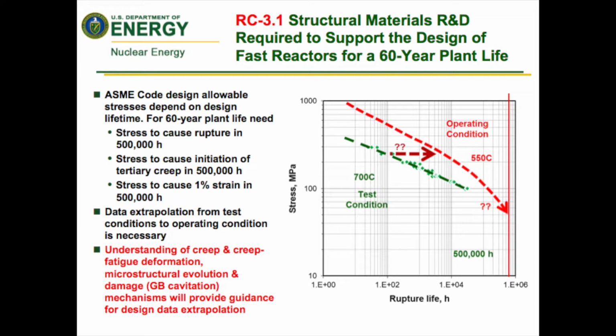So we've got to go ahead and put this thing into test at the laboratory scale. Like all good metallurgists, we like to test at higher temperatures, for instance, say 700 C, even though we may be operating at 550 C. We're going to test at shorter times, but we have to understand what the mechanisms are for the creep and creep fatigue deformation, things like microstructural evolution, the type of damage, for instance, grain boundary cavitation and whatever, that goes on to be able to provide the guidance that we can do the extrapolation of the laboratory data out to the full lifetime, 500,000 hours, effectively the number of hours that exist for a 60-year reactor life, with confidence. And so that's what we're going to be asking you guys to do.